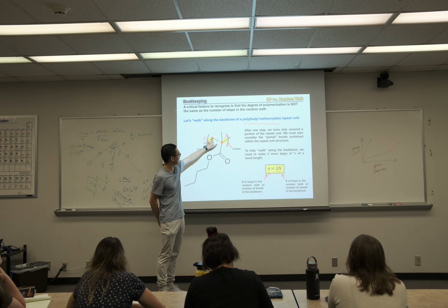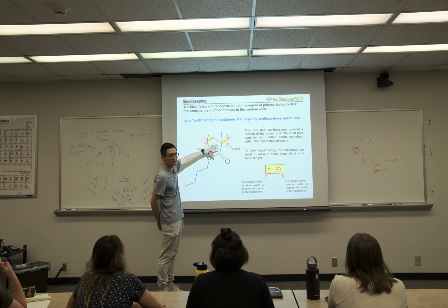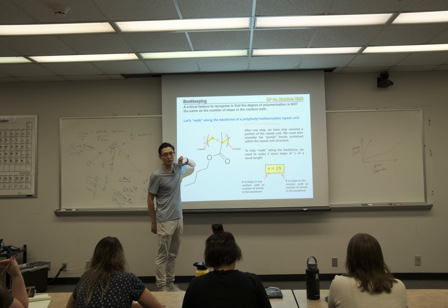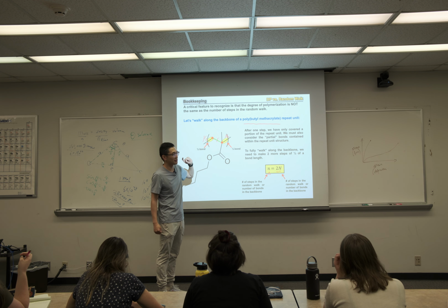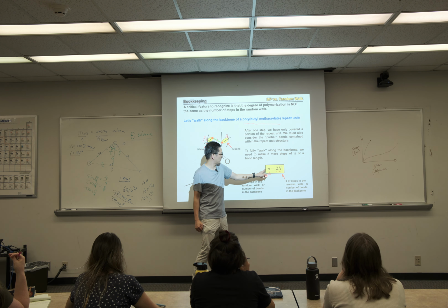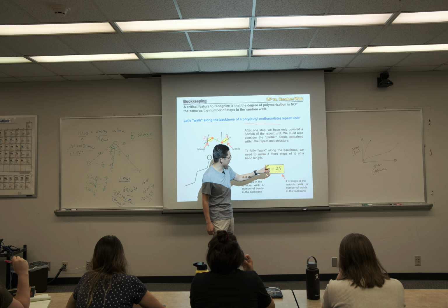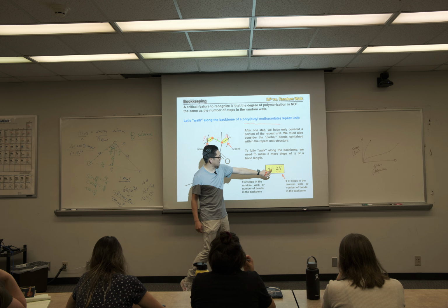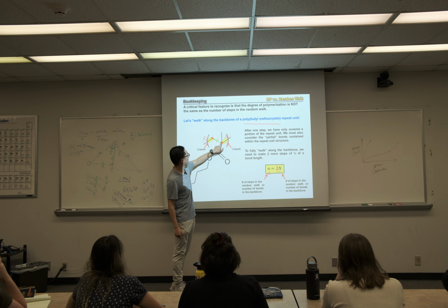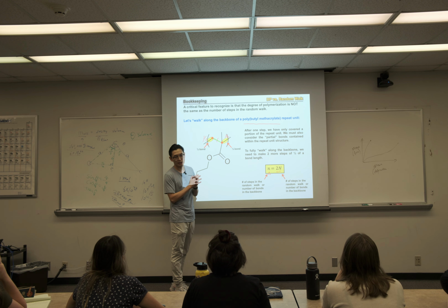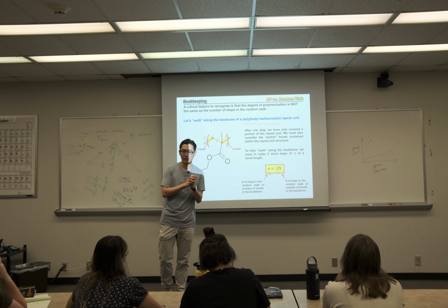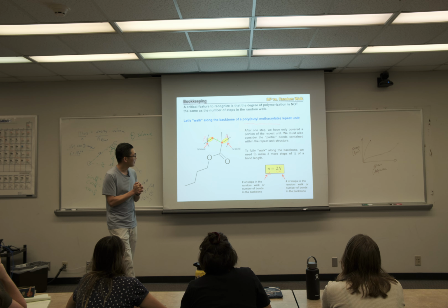But remember, this time our repeating unit is big. It's a giant molecule, so you need to calculate the right one. And you need to calculate the number of bonds along the backbone. In this case, we need to multiply by a factor of 2. Again, this is because there is half bond, 1 bond, half bond. So that's why in this case it matches polyethylene. Okay?